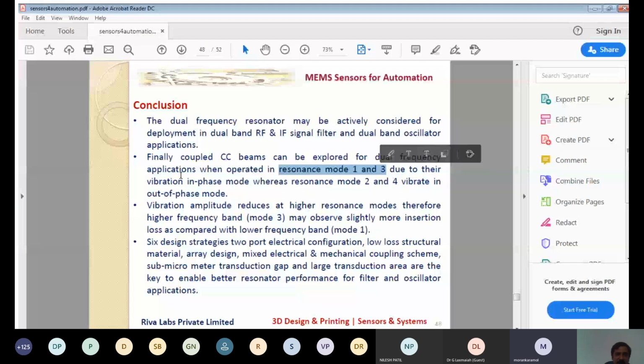Then vibration amplitude reduces at higher resonance modes. Therefore, the higher frequency band, mode 3, may observe slightly more insertion loss as compared to the lower frequency band. So as I showed you in the output also, for mode 3 the output was very less, and for mode 1 the output was more than mode 3. So if you go for mode 5 and mode 7, then the output will be very less. Therefore, we discourage going for mode 5 and mode 7.